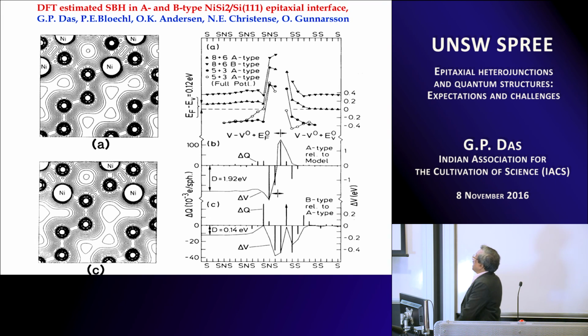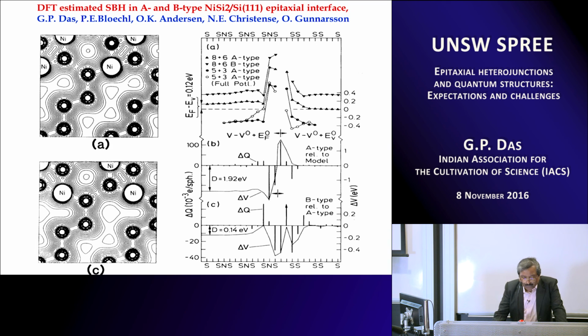This is the last slide, where I will show you how we estimate, using DFT, the Schottky barrier height in A and B type NiSi2 to Si epitaxial interfaces. This work was done way back, but this is one of the first works done on the epitaxial NiSi2 to Si interface. You can see that this is the interface here, this is the silicon 111, and this is the NiSi2, and these are the self-consistent charge density contours, and here is the interface. This is the A-type interface, this is the B-type interface.